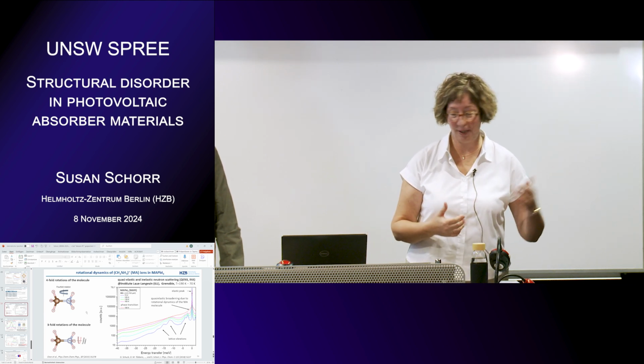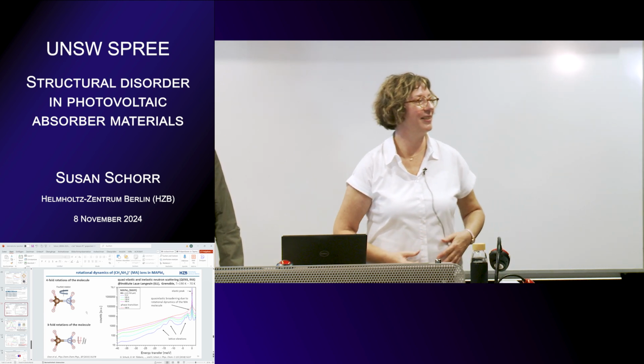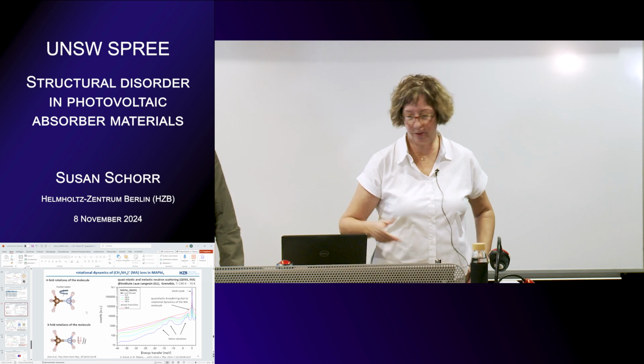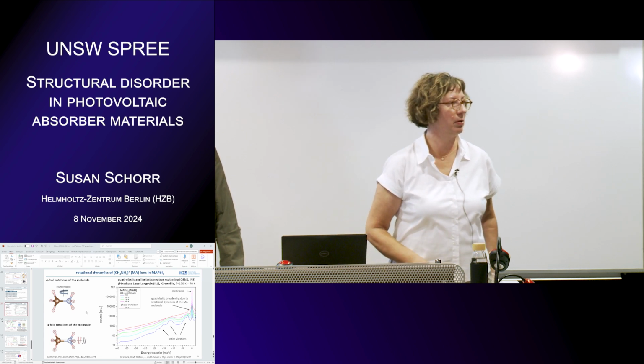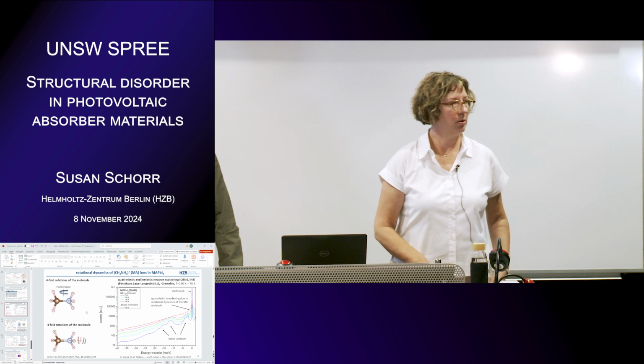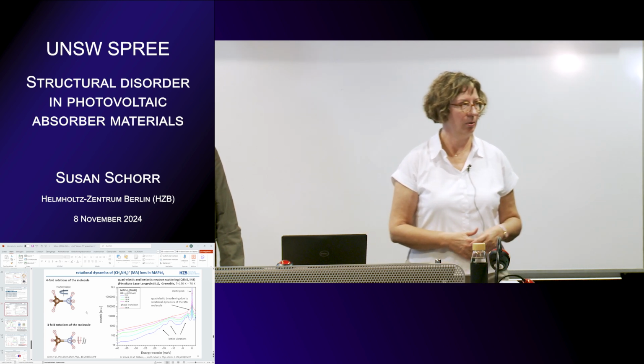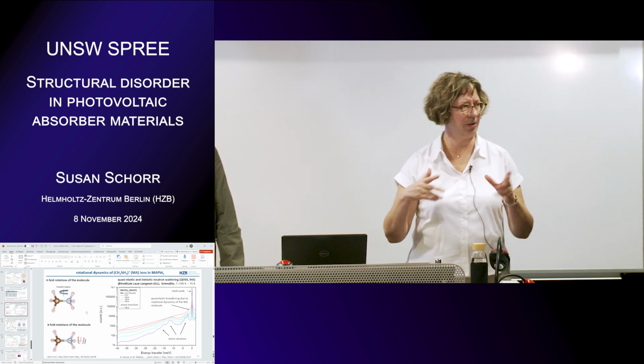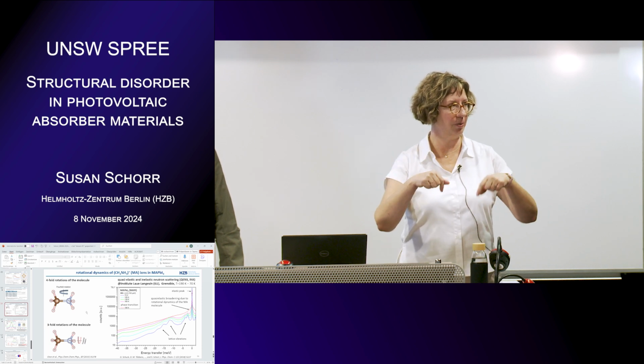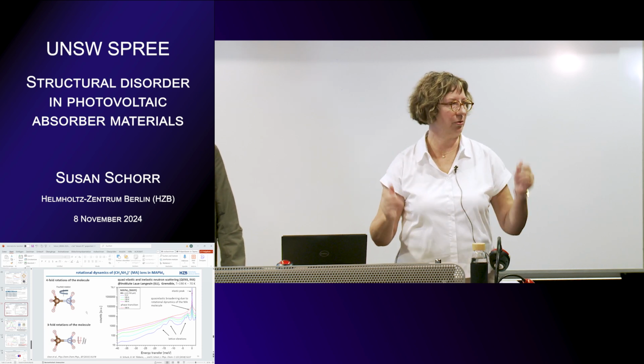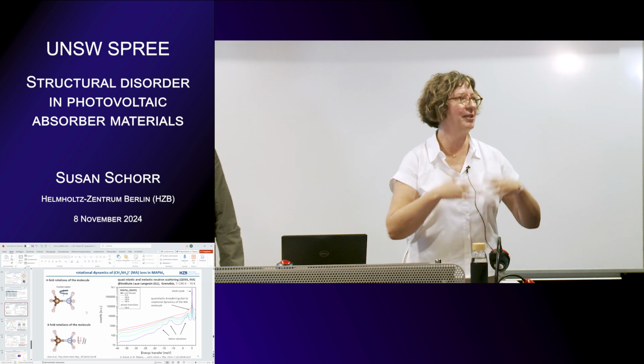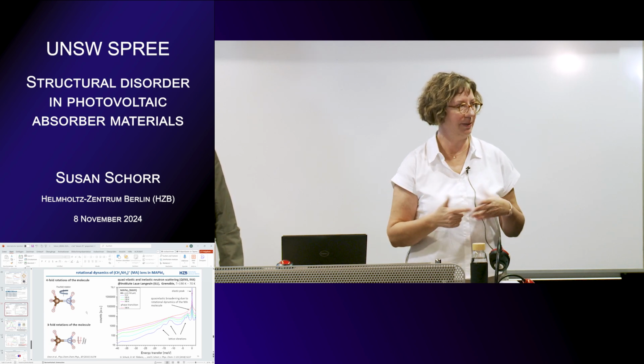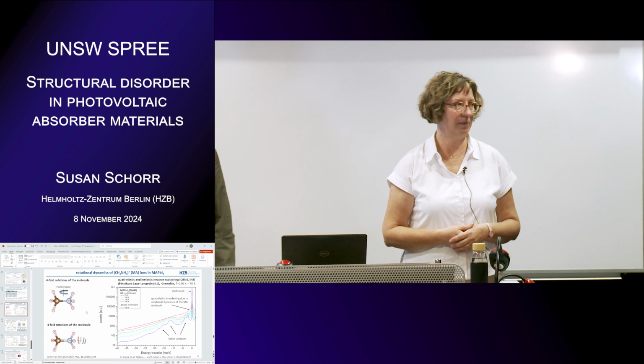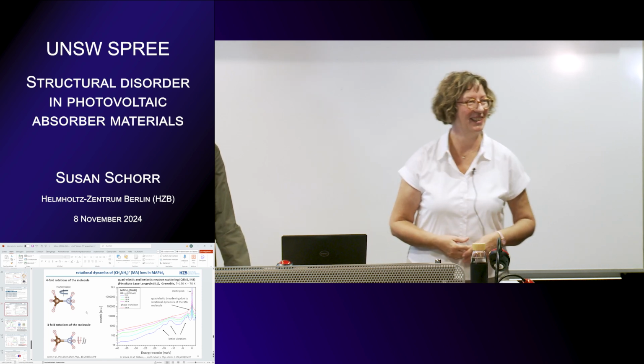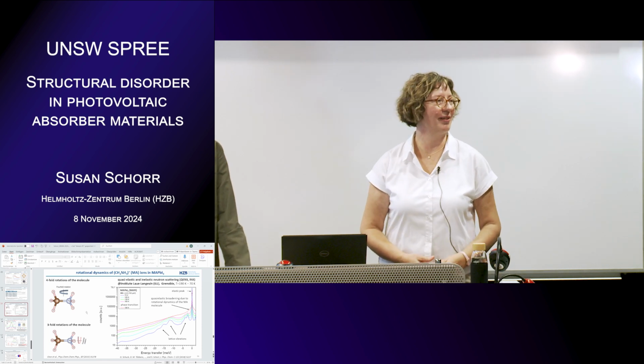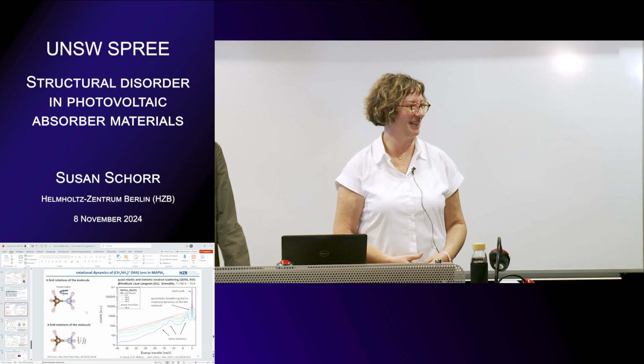So you don't have to go to the ILL. Do you know how they make a powder of that? We made the powder from solution, similar to the single crystal one. You have GBL, DMF or some mixture, then you put the binary precursors in, and then it crystallizes. You have to heat it a little bit, it evaporates, and then you have it. It's very easy, similar to single crystal. Easy and fast, much faster than growing chalcogenides.